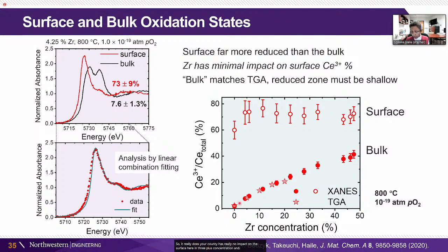And we've sort of validated our experiment overall by showing here that the measurement that we get by XANES in the bulk is the same as we get from the thermogravimetric analysis, which I showed you very early on when I introduced this topic. So those two match up. So we validated our XANES measurement, and we can see now that indeed the surface is far more reduced than the bulk, and it doesn't depend on the zirconium concentration.